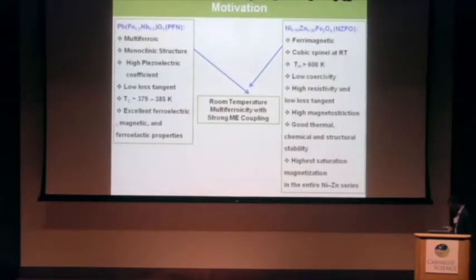So, we have synthesized PFN and nickel zinc iron oxide composite thin films in order to achieve room temperature multiferroism with strong magnetoelectric coupling. Here, PFN is one of the multiferroic materials, and it has a monoclinic structure. It has a high piezoelectric coefficient, low loss tangent, and its ferroelectric TC is around 379 to 385 Kelvin, and it has excellent ferroelectric, magnetic, and ferroelastic properties.